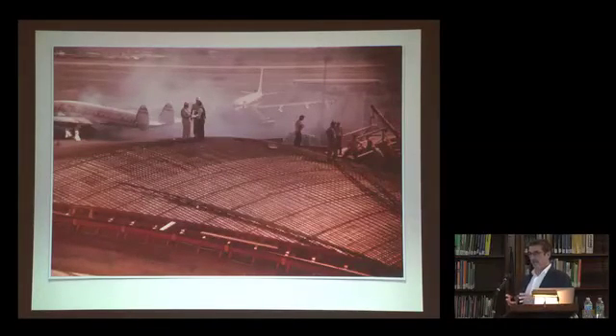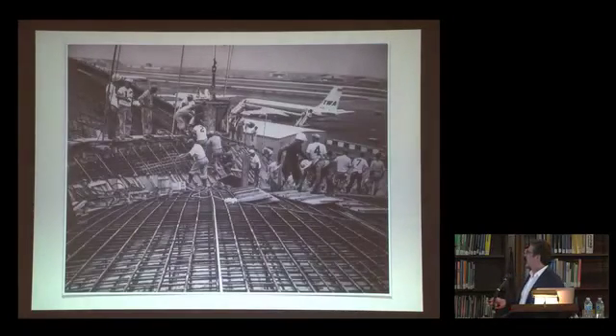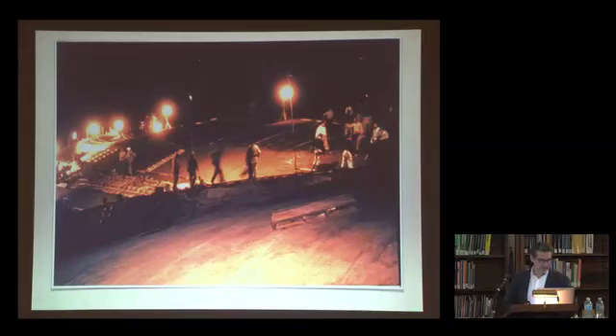But with those 55-gallon buckets of cement coming up, the pour of the larger shells was about 30 hours each. And actually, here they're starting, and they had to do this by day, and here's one of those buckets, and they had to do this by night. So a critical moment after the cure of the concrete was the slow and careful removal of the scaffolding support system below. The concrete was cured by keeping it wet for almost 3 weeks, and no scaffolding was moved until the compressive strength of the concrete reached 4,000 psi. They had cores that they were measuring and testing, and nobody, I'm told, touched anything until that happened.